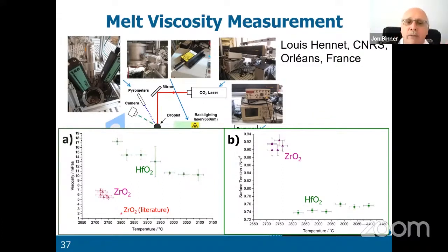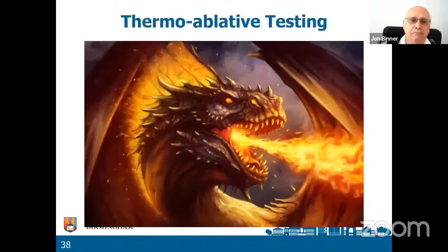So we've now got values for surface tension and viscosity. And if you look at those values, you realize that the viscosity is really low. So we are not getting protection at all from our molten oxide. These are fragile liquids. This material is not going to survive an oxyacetylene torch's gas blast at very short range. So we need to find another explanation.